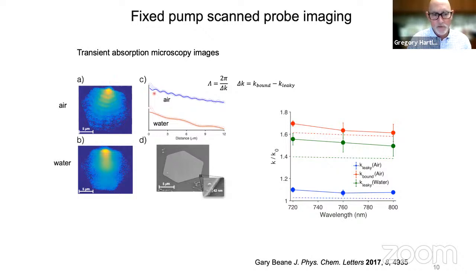This is a slice down one direction of this plate. The wavelength depends on the difference in the wave vectors of the bound and leaky modes, and we can calculate that. We get almost perfect agreement with what we measure. If we do our little trick of Fourier space imaging to measure the wave vector of the leaky mode, we can then from this measurement get the wave vector of the bound mode, which is actually not that easy to do. That's what's done over here. The blue dots are the leaky mode from these Fourier plane images, the red dots are the bound mode, and the lines are the calculations. Don't worry about the green dots, they didn't work too well.